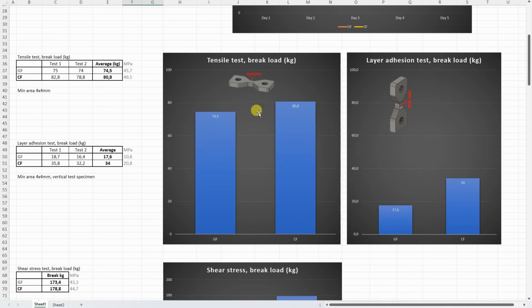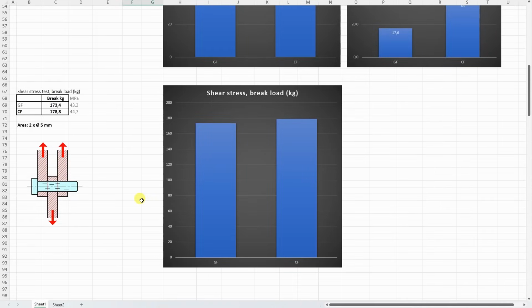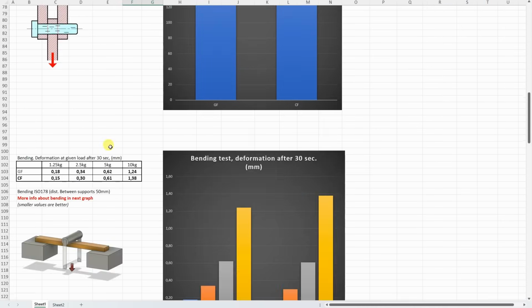On the tensile test, the difference was not so big, but the carbon fiber was a little bit stronger. Now on the layer adhesion test, the carbon fiber is very good, but the glass fiber is quite weak. Anything below 20 kilograms is not acceptable from my side. On the shear test, the orientation of these fibers really helps if this is printed in horizontal position, so it was very strong in this kind of test.